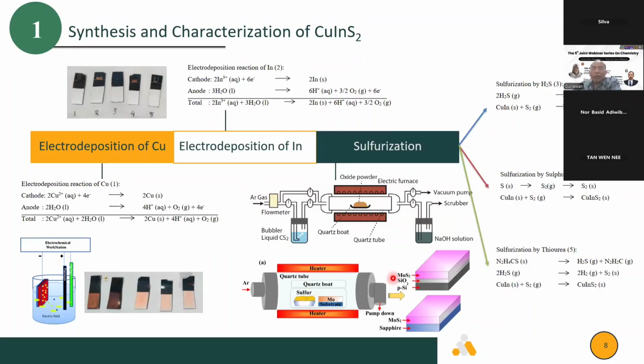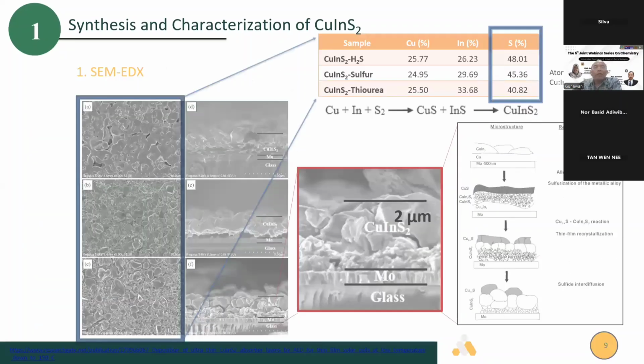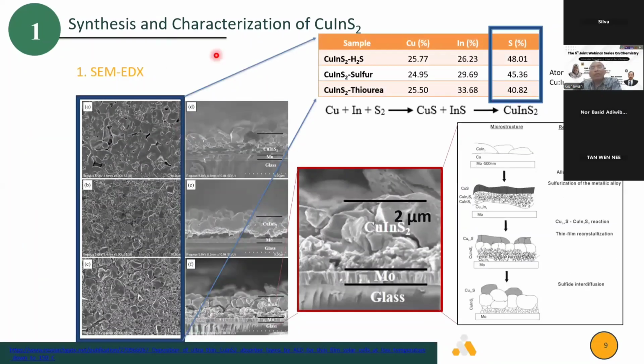So then we can continue. Here is the reaction actually. From the characterization, we use EDX here, and here for the surface analysis using SEM, and this is the cross section of the SEM, copper indium sulfide. You can see that the result is porous copper indium sulfide. And also we can see the EDX. Here we can see the S.